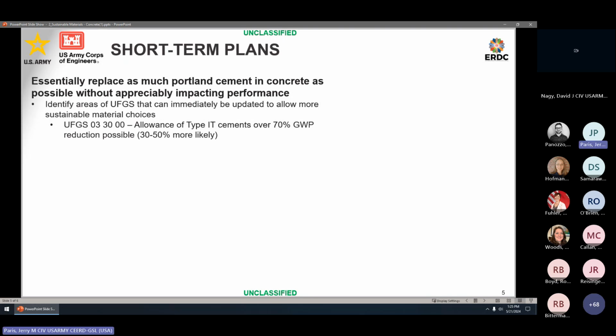These have the ability to reduce emissions by up to about 70%. The more realistic case is probably going to be 30 to 50% as they are delivered to the concrete ready mix producer, so that they can do replacements in the field or at the ready mix facility as necessary based on the project. But we can pretty much almost hit those targets today. So those are now allowed in the cast in place spec.